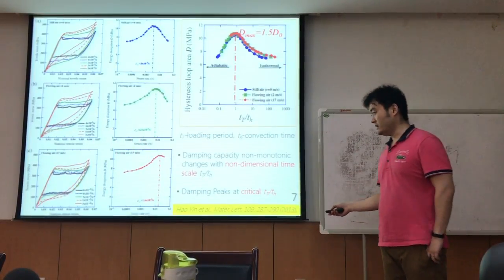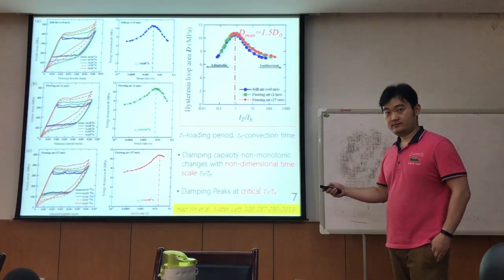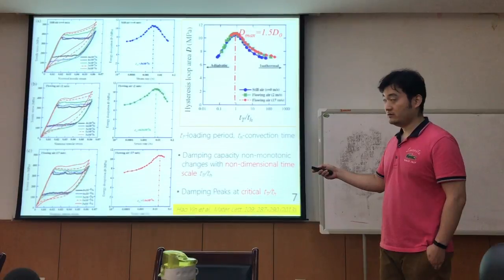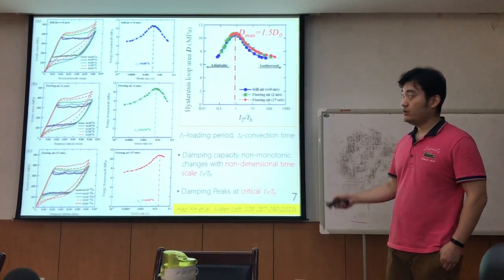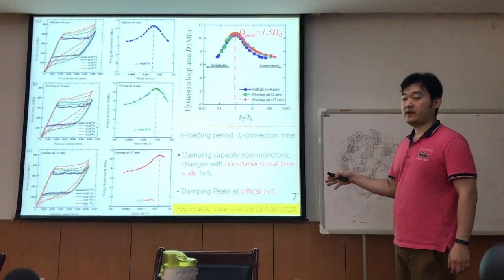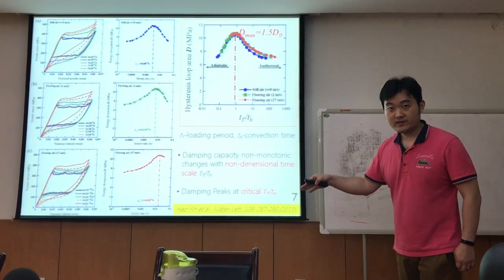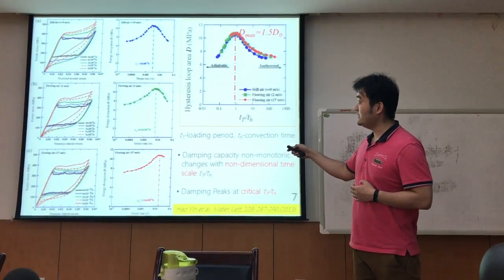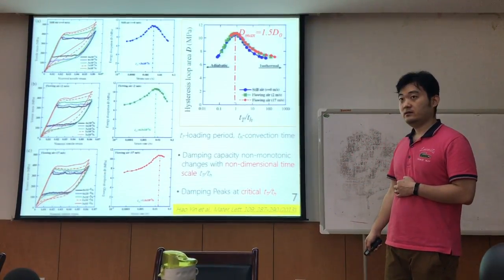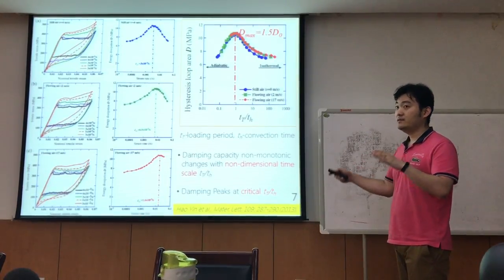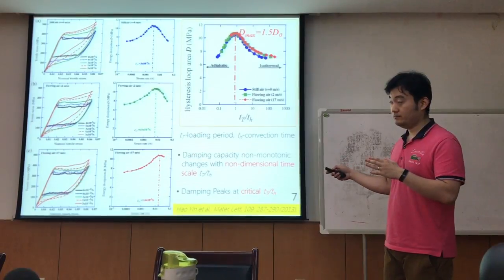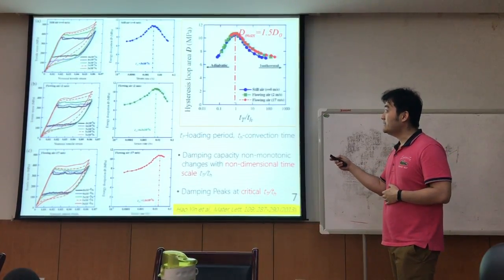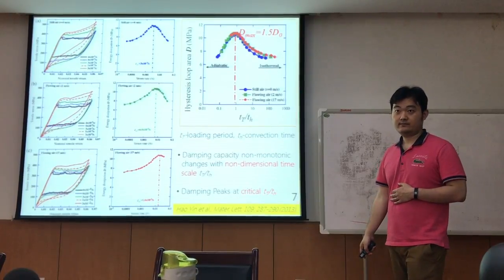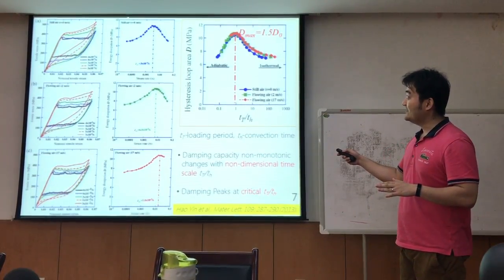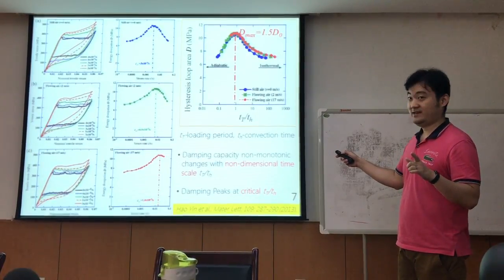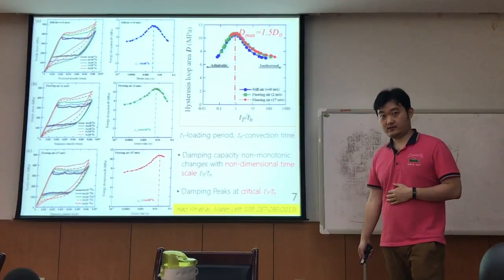So in 2013, we did a set of tests under different ambient conditions by using different air velocity and different strain rate. We found that the hysteresis heat, which is the area surrounded by the stress strain loop, and it can represent the material's energy dissipation ability, varies non-monotonically with the strain rate. And we found that in different ambient conditions, the peak happens at different strain rate. Okay?